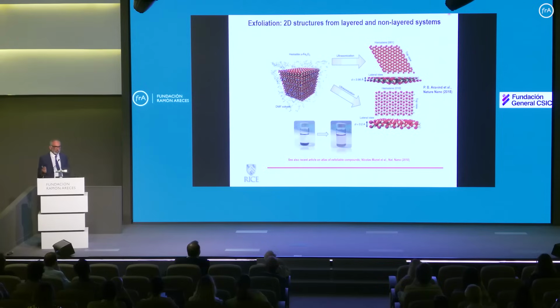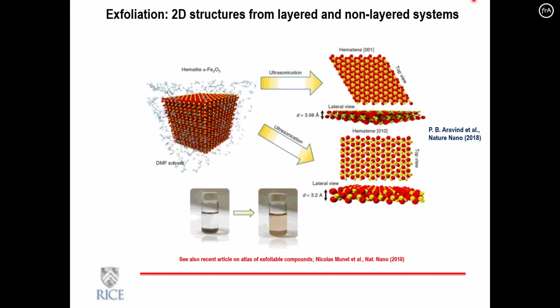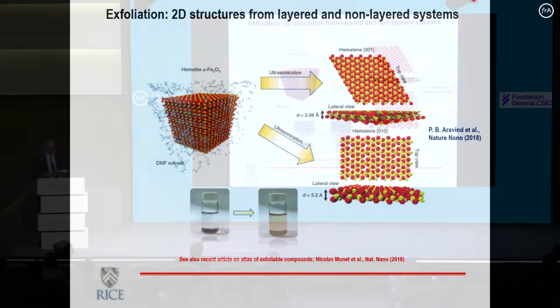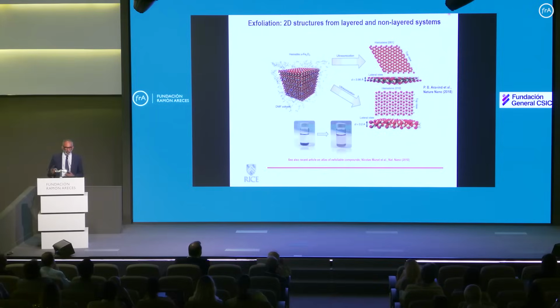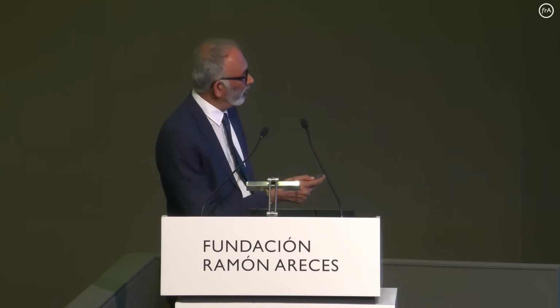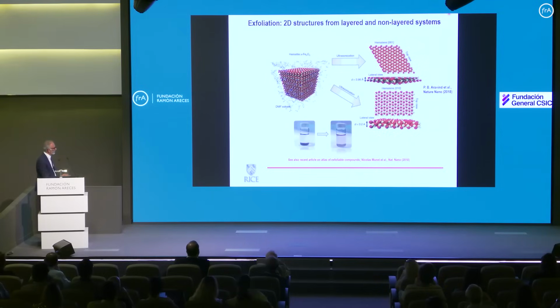The question again is, how do you controllably make these materials? There are multiple ways of doing it. Think about graphite as a layered structure, a deck of cards, for example, and how do you really extract individual cards or individual layers? One simple way is to peel it off one by one. And you can do that physically by peeling layer by layer, or you can peel the whole thing using some kind of a solution exfoliation approach. And a lot of people are now beginning to look at exfoliation as a method to make bulk 2D materials.